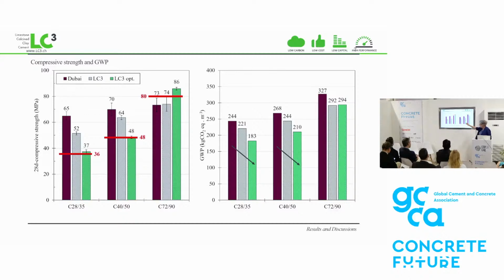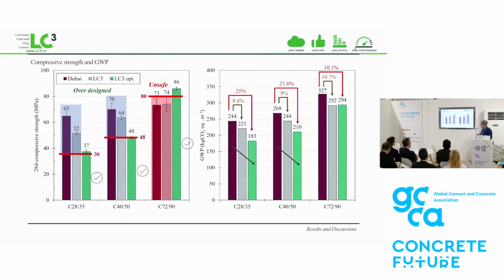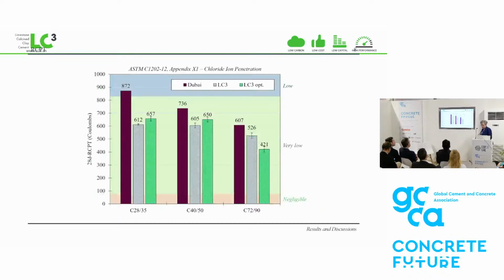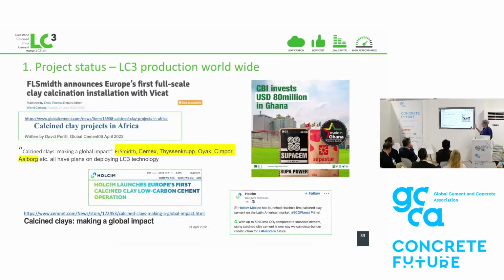So after redesign, we got the results in green there, and when we look at the CO2 savings, we could see for the two lowest grades, we have a saving of between 20 and 25%, and even for the higher strength grades, where we had to achieve a higher strength, we could still save 10% of CO2. And these are the results for the chloride ingress by the rapid chloride permeability test. And you can see all the LC3 results are in the very low category, whereas some of the concretes in the current code were actually only in the low category. So these are some of the announcements from around the world.